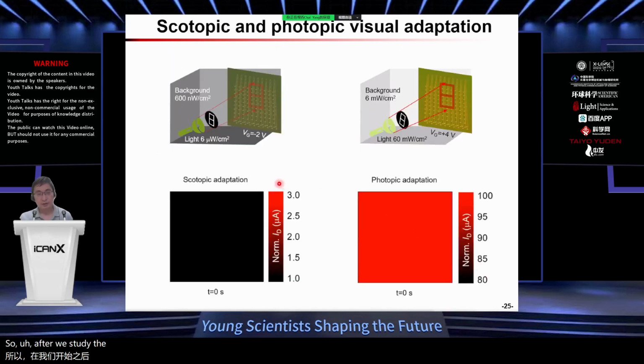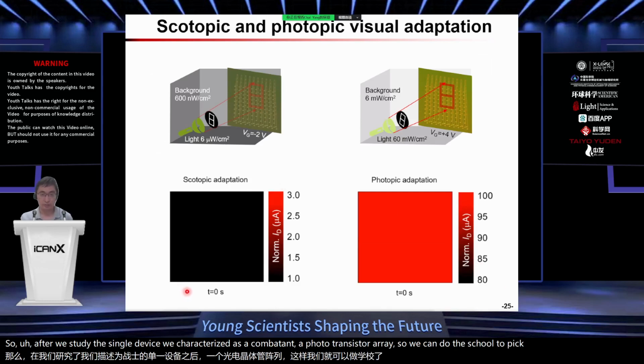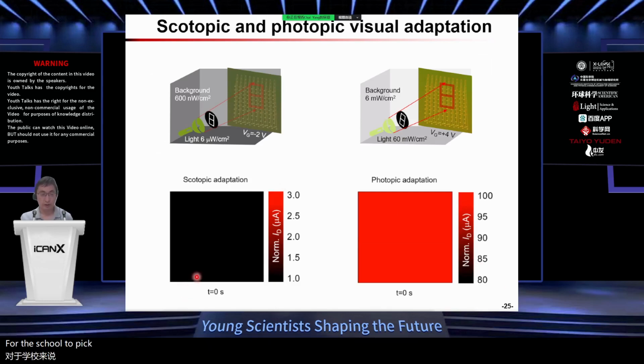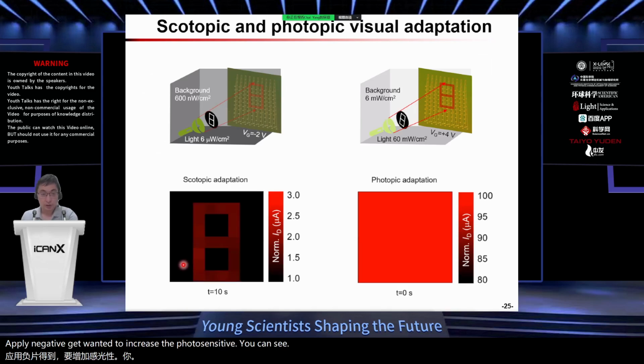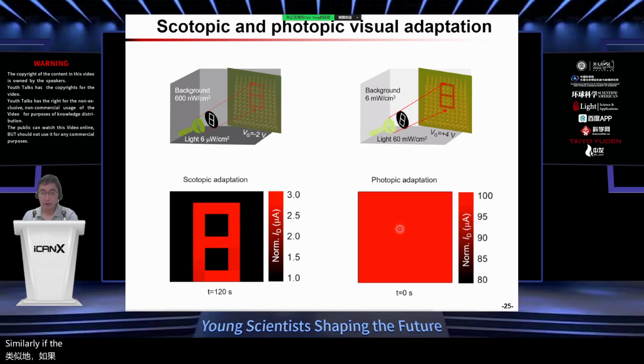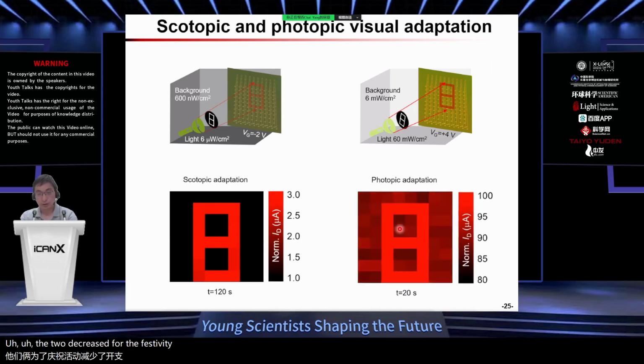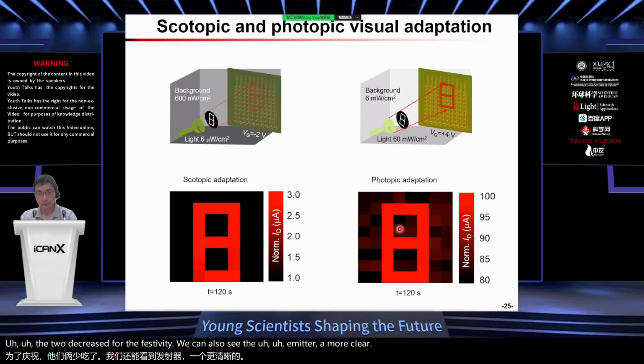After we studied the single device, we characterized the 10 by 10 phototransistor array. We can do the scotopic adaptation and the photopic adaptation. For the scotopic adaptation, at the very beginning the background is very dark and we cannot see anything. But if we apply a negative gate voltage to increase the photosensitivity, you can see the image automatically becomes clearer and clearer, so we can see its shape. Similarly, if the initial condition is very bright, we still cannot see anything. But if we apply a positive gate voltage to decrease the photosensitivity, we can also see the image more clearly.